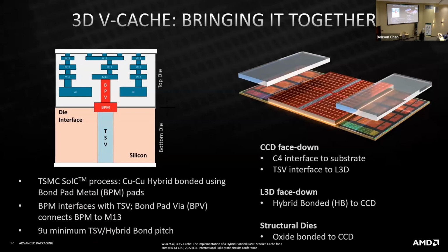So how do we bring this all together? We are using hybrid bonding. In this case, the bottom die is the CCD die, which is thinned down to reveal the TSVs, and it is connected to the top die using BPM, the bond pad metal, as you see in red. The bond pad metal is connected to metal 13 using the BPV, the bond pad via, as you can see in the picture. The current pitch is a 9 micron minimum TSV pitch, and this gives you the 96 MB cache offering. The CCDs that you see on the east and west in this image have structural silicon that is oxide bonded on top of the CCDs to allow for thermal dissipation.